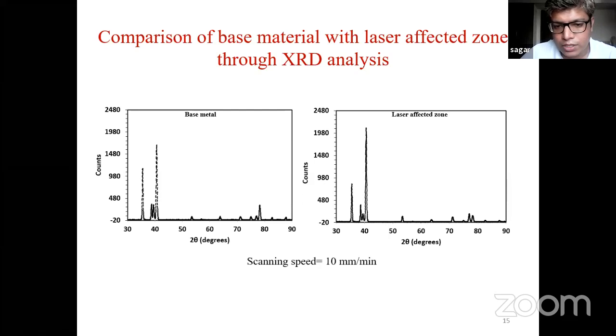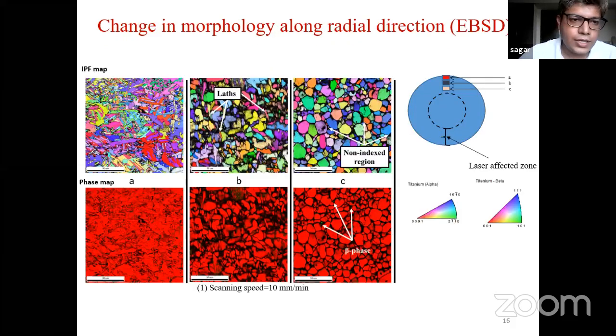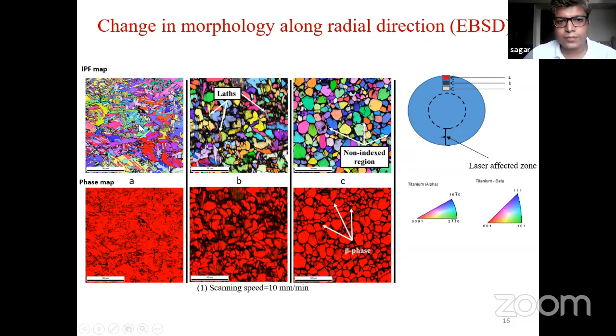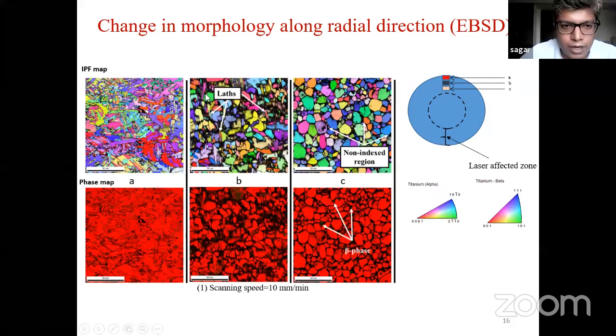So to see what happens at localized level, we have to do some more scanning. We have to go through EBSD analysis as well as TEM analysis. So let's see what those analyses have brought up. If you see over here, there were three kinds of structures forming. Very near to the laser affected zone, this is the structure, where you could see many kinds of dendritic structures. Then the B structure shows some kind of dendrites or laths, but overall some equiaxed grain structures also. And at the C zone there is the equiaxed grain structure with some boundaries where we could not see any orientation or anything.